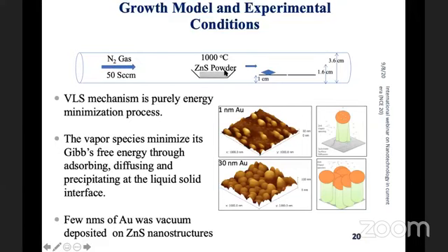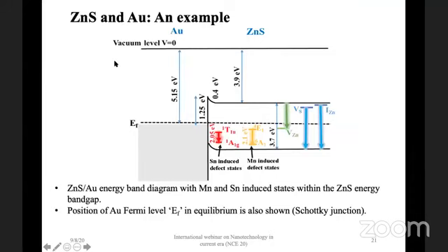So this is the experiment we did. We had the zinc sulfide powder centered in the horizontal tube, and took the temperature to 1000 degrees. We had the substrate placed at a certain distance, where the temperature was between 700 to 800 degrees Celsius. We had nitrogen gas, which took these vapors to the substrate. The substrate already had metals coated onto it, and then we grew the zinc sulfide nanostructures. Finally, we did vacuum deposition of gold on these nanostructures. Just to give you how the band structure looks like.